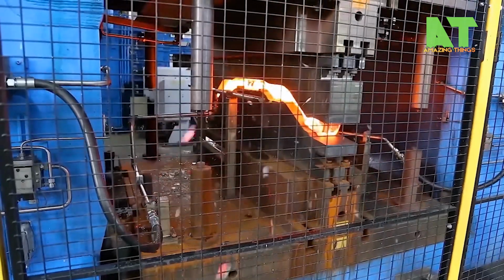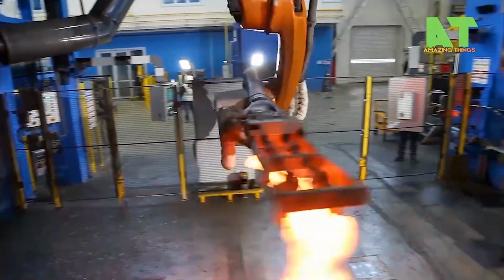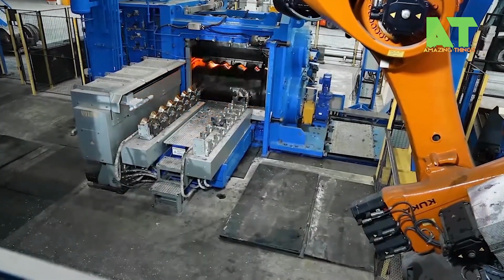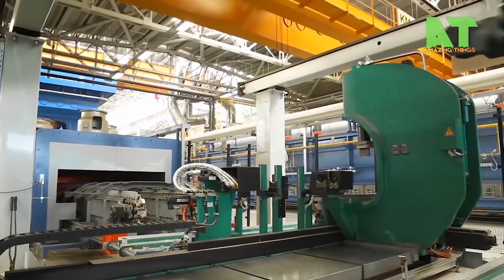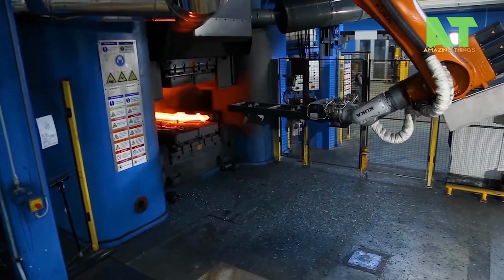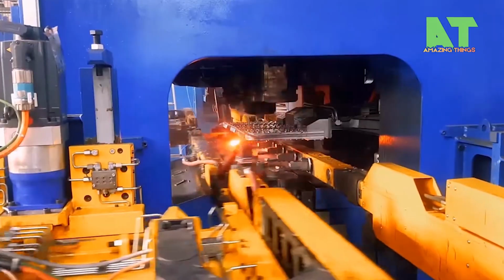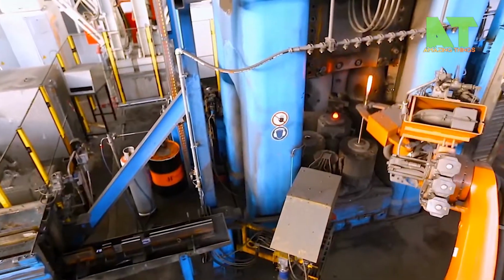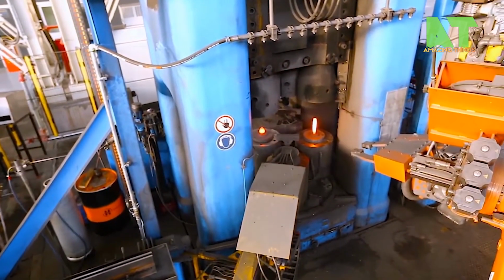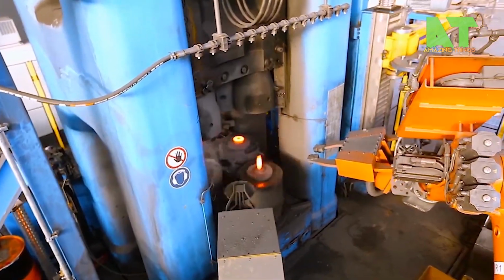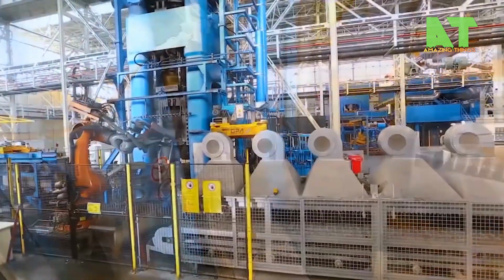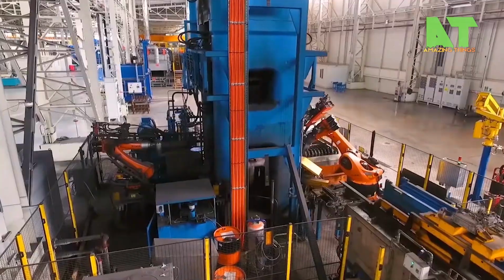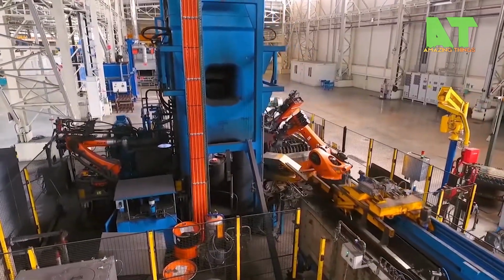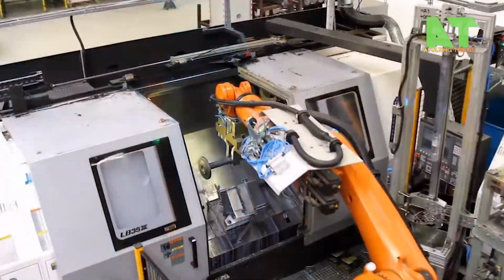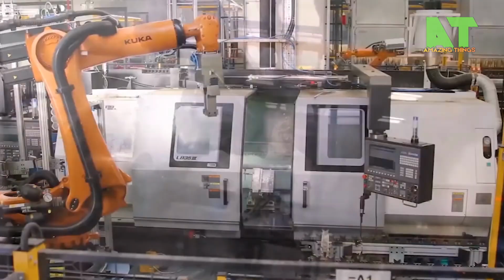The bars are heated in induction or gas furnaces to forging temperature, around 1050 to 1150 degrees Celsius. Then they're fed into hot stamping presses, which form the cambered arc shape of the spring leaf in one or two powerful strokes. After forming, each leaf goes through a closely monitored heat treatment cycle, quenching in oil or polymer, then tempering, to develop the precise hardness and toughness required. Too hard and it'll crack, too soft and it'll sag. Getting that balance right is what separates average springs from ones that last.